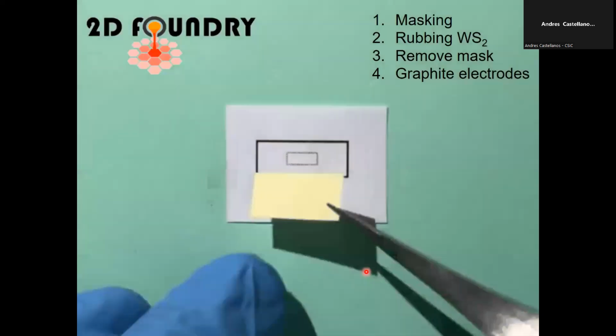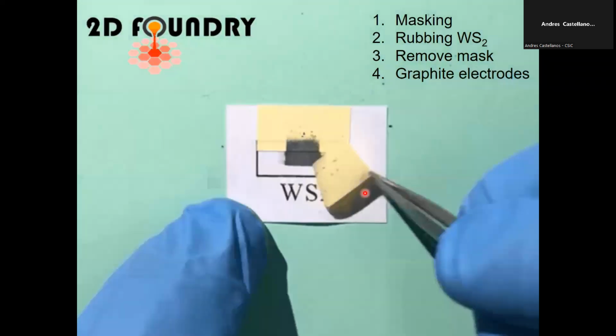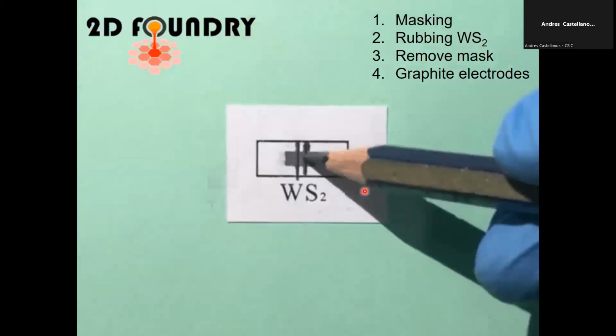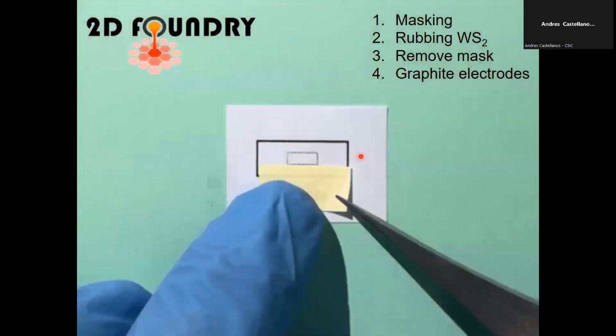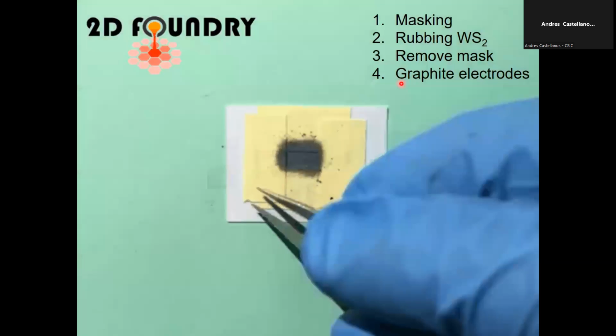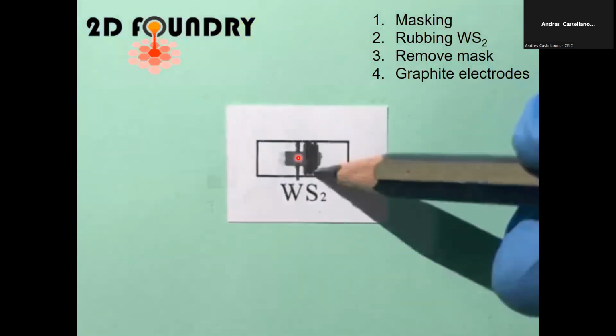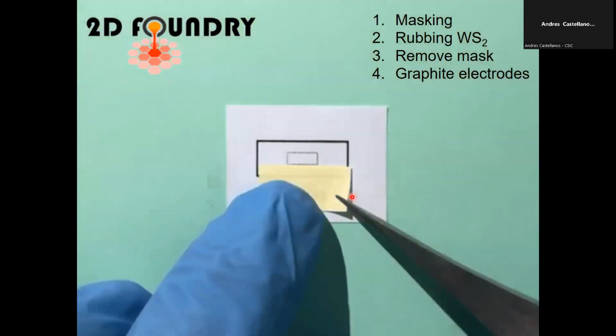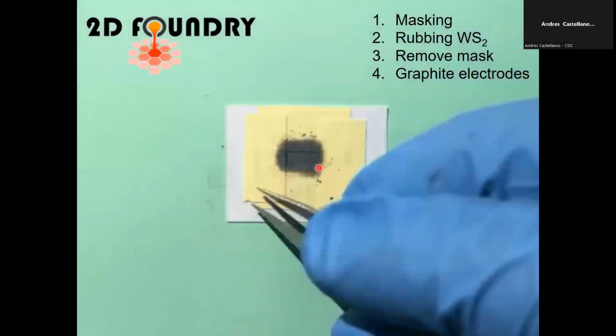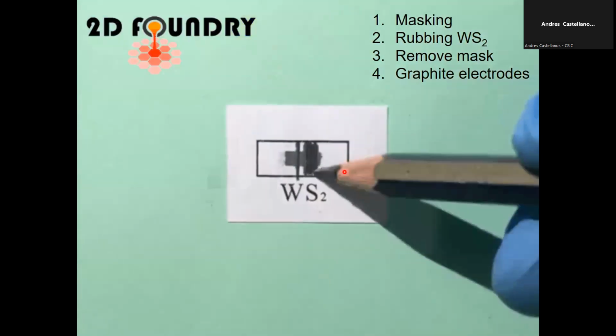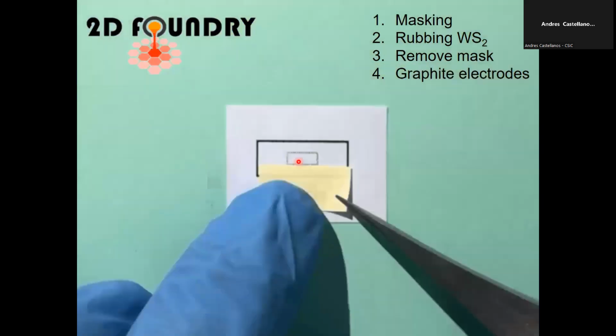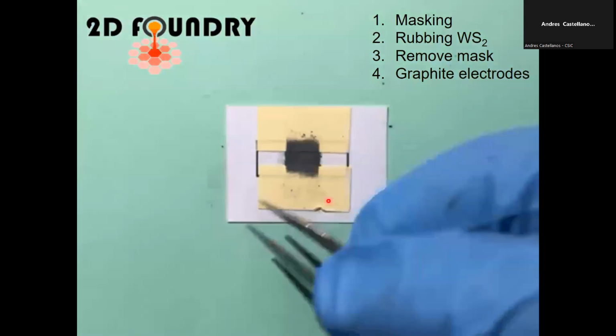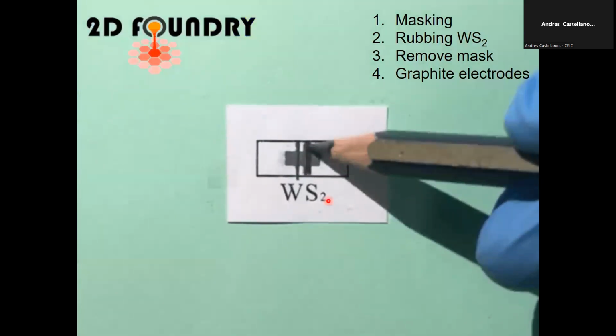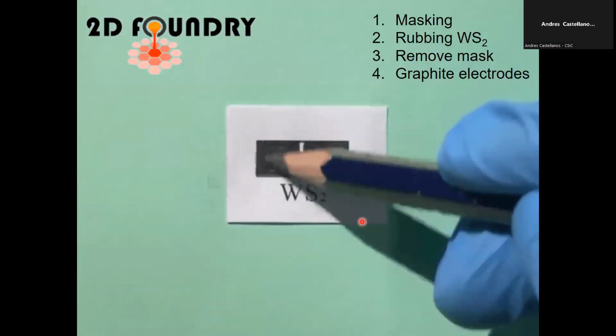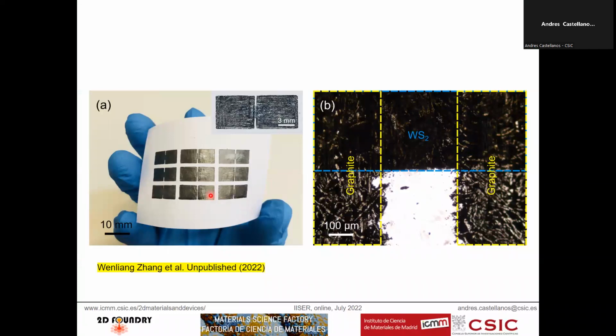Basically, we are integrating different van der Waals materials on paper substrates, using just a dry process, directly rubbing. You can buy powder of tungsten disulfide and rub it with a cotton swab, as you will see now, and it creates a film of tungsten disulfide on the surface of the paper. Then you can use a graphite pencil to put electrodes on it. Like this here. So it's a very simple way of fabricating photodetectors with your van der Waals materials.